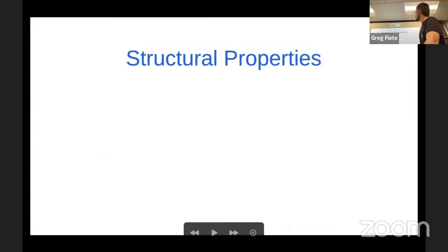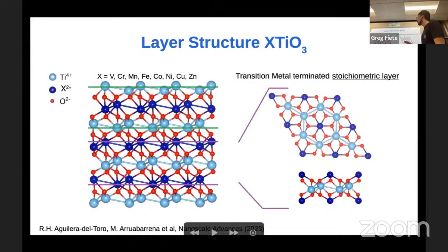If we move to the structural properties of ilmenites, I have already told that this compound is exfoliated in the 001 direction, but this can be done in several ways. One might think, for example, to cut it at the titanium atoms and get this layer, or you can do it transition metal terminated. There are different ways. We analyzed many possibilities, and we concluded that for all of our compounds, the transition metal terminated stoichiometric layer was the most stable.